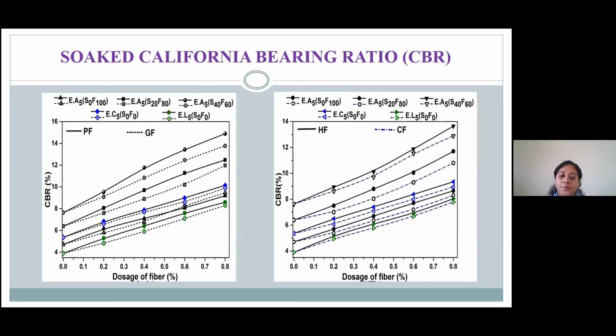During soaking, the slag can produce silicate hydrates, leading to less attraction of moisture in the soil. This combined addition of fly ash with slag in the AAB soil helps to increase strength and stiffness, basically forming a bridge when the geopolymerization reaction is taking place.